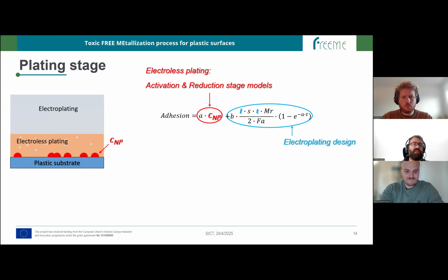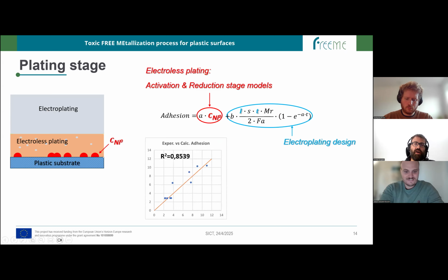Later on, since we also have an adhesion between the two layers, we also introduced into the model a second level of relationship related with the electroplating process, and the development of the layer over the electroless layer. And by this means, we have developed an approximation function to predict the adhesion based on the different operating conditions, having also higher than 0.85 R-square fitting performance.